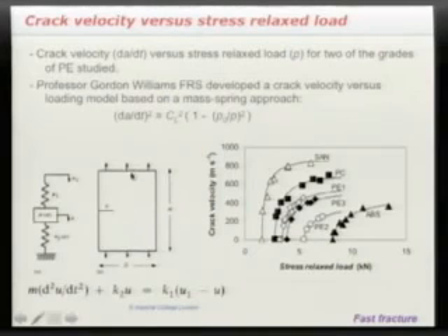As you load this to different levels, you can model the system by considering it as a spring mass system. So you have here the mass of the sample. In fact, the moving parts of this sample were determined by the crack length. So in fact, the mass was a function of crack length. And the stiffness of the sample was also a function of crack length as well, because as the crack grows, the whole thing becomes more compliant.